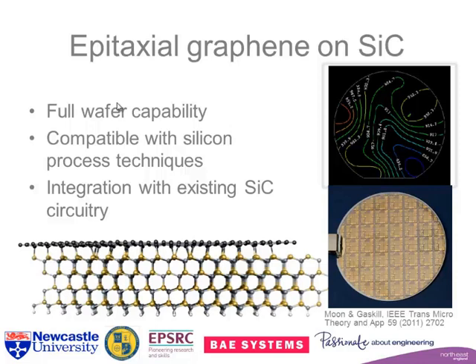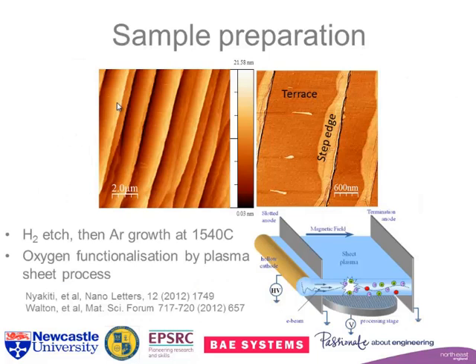So the big plus for us, well, we can stick it through standard silicon process technology, so we can go down the lab and do things as we would normally do, and we can integrate it with existing silicon carbide circuitry. So here is a model of the silicon carbide underneath. The graphene layer is actually the one above this. This is the interface layer, and you can see that we have chemical bonding between the silicon carbide and this interface layer, and then there's further bonding into the graphene above. That is a big difference in comparison to what you get with the Scotch tape material.